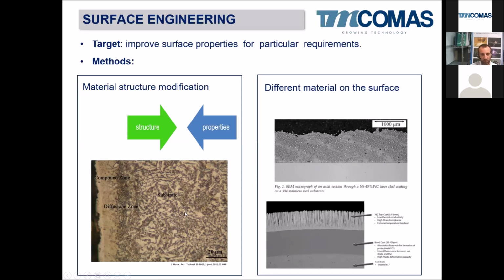After that, the substrate is more or less non-affected, non-modified. On the other hand, we can also apply a coating completely different from the base material, with a lot of different techniques to apply these coatings. But these coatings will act in a different way because it's a completely different material than the base material. So in this case, for example, it is a laser cladding of spherical tungsten carbide. Here you can see all the tungsten carbide spheres in a matrix of nickel alloy made by laser cladding. So this picture clearly shows us that the surface of this bulk material is no longer made of the base material, but of a tungsten carbide layer. So the hardness and the wear properties will be completely different.